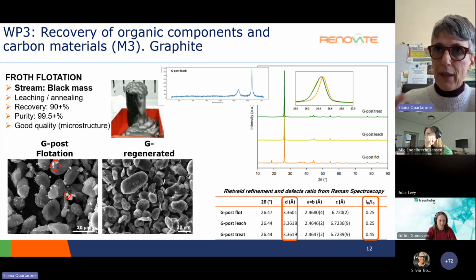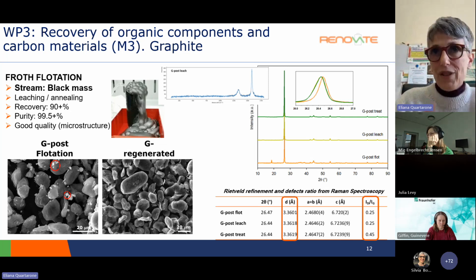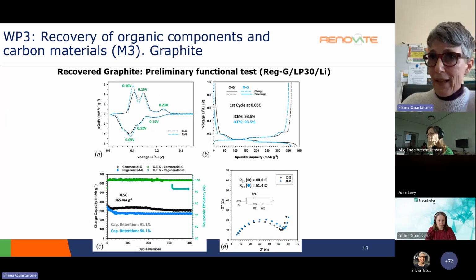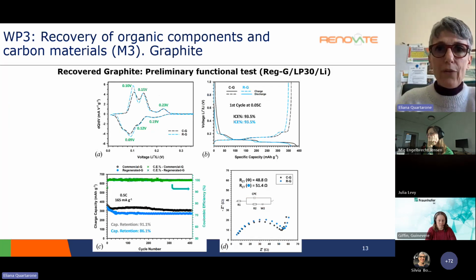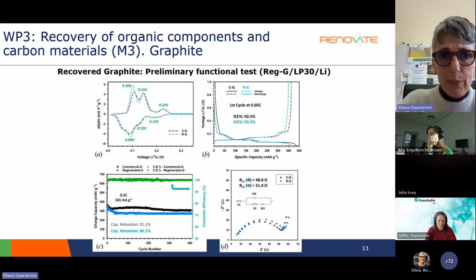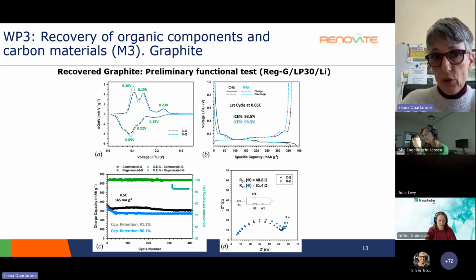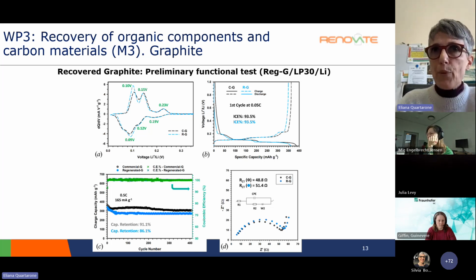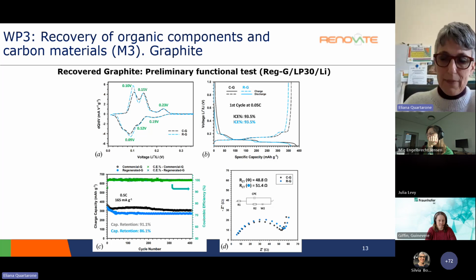So you can check here the order-disorder properties of the graphite, but also the structural component and the microstructural order and crystallographic properties of the graphite. We are at the stage of the preliminary functional test because we are now comparing a fully recycled graphite with a commercial benchmark. And as you can see here, the results are really promising. Of course, we can add further improvement there, but in any case, we have quite good capacity retention after 400 cycles, and a very good ICE, which is in pretty nice agreement with the commercial systems.